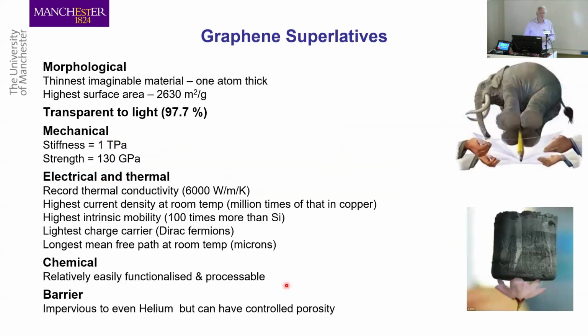quite interesting properties. These were some of the properties that people started to identify early on with graphene. It was the thinnest material you could possibly have. It's only 1 atom thick, a third of a nanometer thick. So that's the highest specific surface area of any material. It's almost transparent to light. It absorbs a little bit of light, but it's nearly transparent to light.